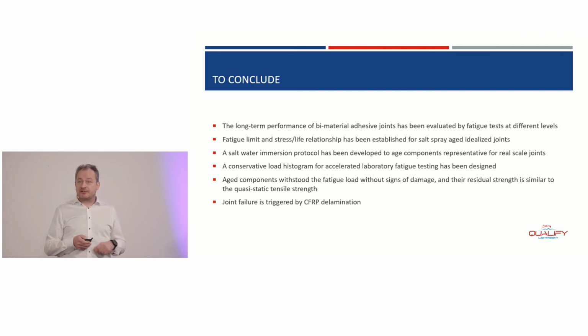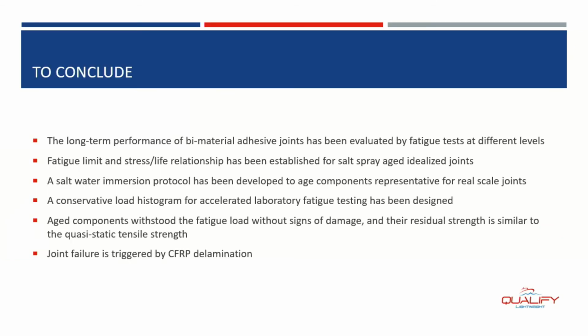So to conclude this presentation, I can summarize that we have investigated the long-term performance of the adhesive joints by testing at multiple levels. Fatigue limits, stress-life relationships have been established after salt spray aging at idealized joints. For the large components, we designed a saltwater immersion bath to mimic the exposure to operational conditions.